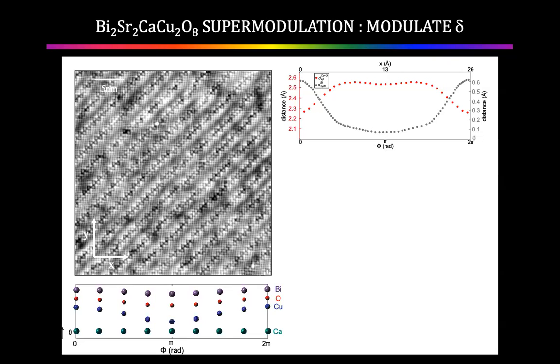So what they tell us is that when the bismuth atom is at its maximum displacement, the distance between the apical atom and the copper atom is at a minimum. And when the bismuth atom is at its minimum displacement, the distance between the copper and the apical oxygen is at a maximum. That's because the amplitude of corrugation in the top surface is smaller than the amplitude of corrugation in the plane. There's no one who disagrees about that.